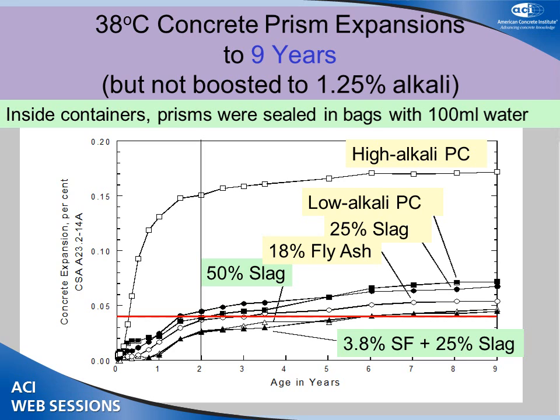We measured the concrete prisms over 9 years in the laboratory at 38 degrees, sealed in bags with a bit of water inside containers at 100 degrees Fahrenheit. And the 0.04 limit is the red line across the horizontal axis there. 2 years is the standard number, which is the vertical line there. It's 2 years. You can't see the numbers. And what you see is the high-alkali concrete, even without the boosted alkalis, took off very rapidly, within about 3 or 4 months exceeded that limit.